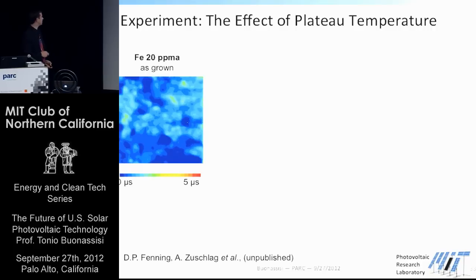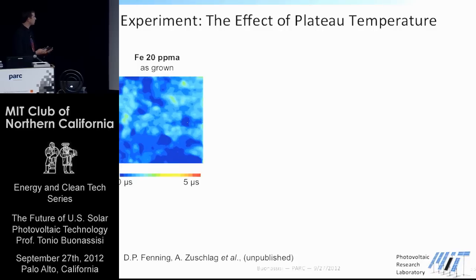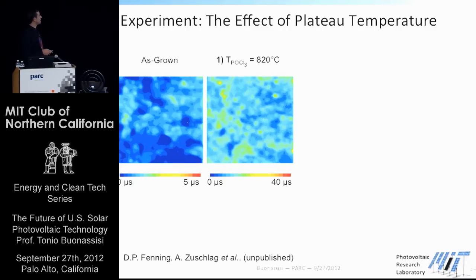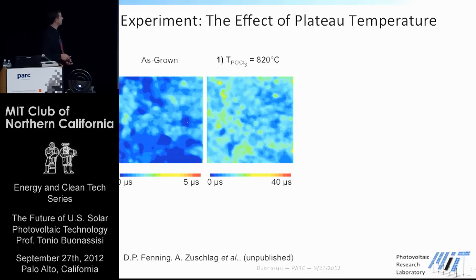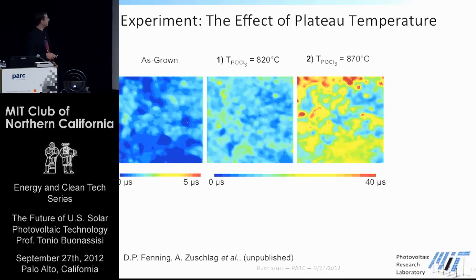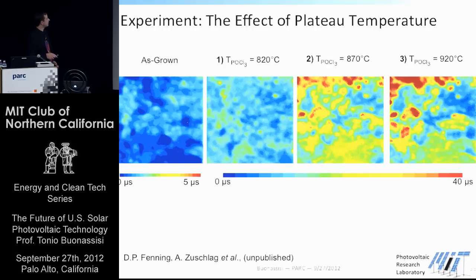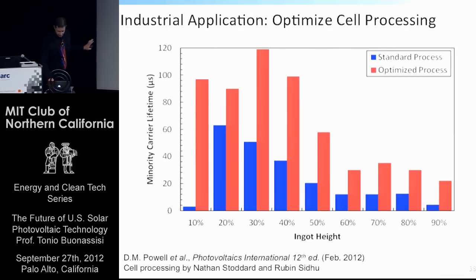And what we see, just as an example, if you start with a pretty heavily contaminated material, this is the as-grown case. This is the minority carrier lifetime showing you the electrical performance of the material. As you try a standard process, we'll call it 820 degrees C, you improve the material a bit. You can see the scale bar has changed now, about a factor of 8 improvement. But as you go to higher temperatures, as predicted by the model, you get an even further improvement as you're dissolving these impurity clusters within the material. And the cool down has to be tailored just right to be able to get those dissolved impurities out of your material. I'll breeze through the following slides, which is just experimental validation.